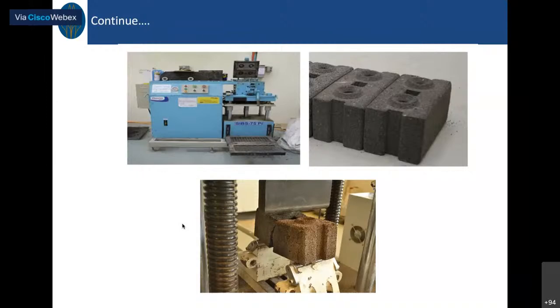Dry mix, meaning we put it in the machine, we press it under pressure, then it will have its shape. So no need to put it in the mold for 24 hours. Similar thing for geopolymer concrete. In geopolymer concrete, there is no cement at all. We are using a different material to bond the material and the rubbercrete inside.